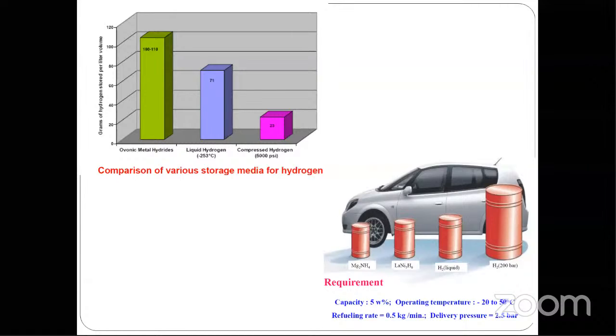Basically, the Department of Energy of USA has a target for transport vehicles: we need a storage capacity of around 5-8%, and the operating temperature should be minus 20 to 50 degrees centigrade. And the refilling time should take only 1 minute for refilling around 0.5 kg of hydrogen. And the delivery pressure from the solid cylinder should be above 2.5 bar, because this has to supply the fuel cell to generate the electricity. So these are the storage container requirements from the Department of Energy USA, called DOE. They have set some conditions to design the proper storage tank for hydrogen based vehicles.